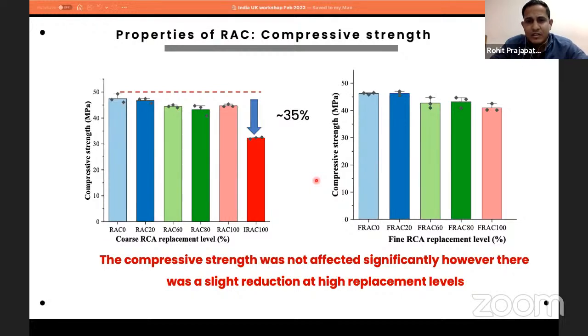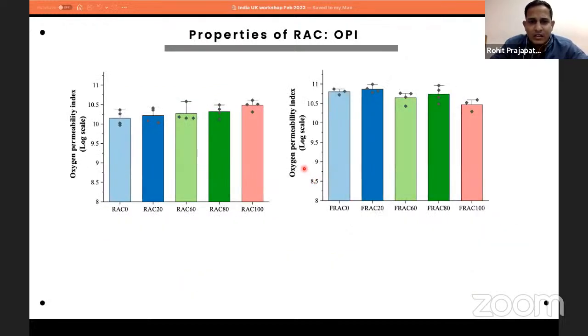We also have done the durability test. One of them I'm just presenting here. We have the oxygen permeability index. So we could see that all replacement have comparable performance. And durability is a big problem in case of recycled aggregate concrete, especially when you use fine RCA.